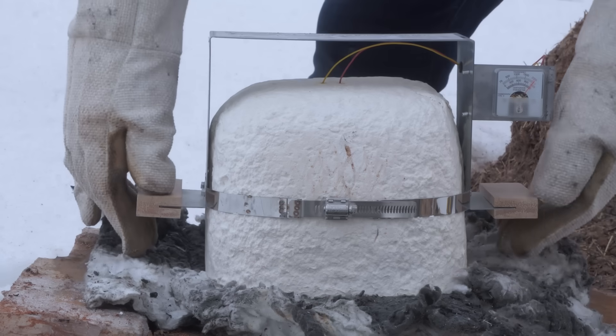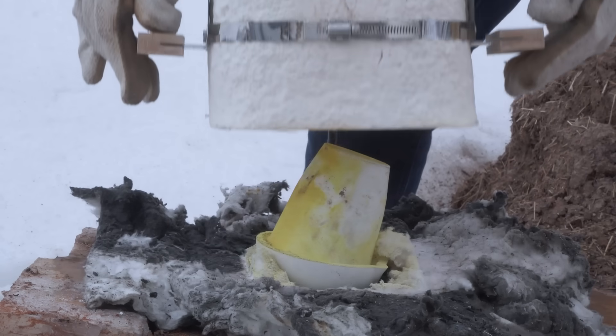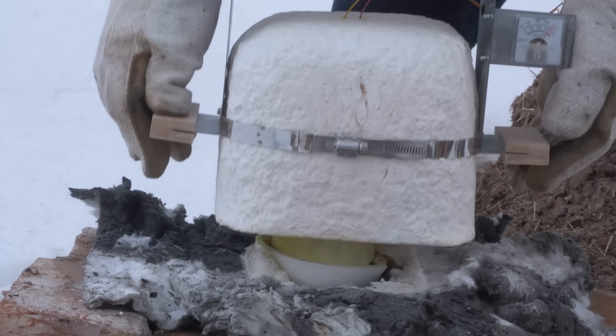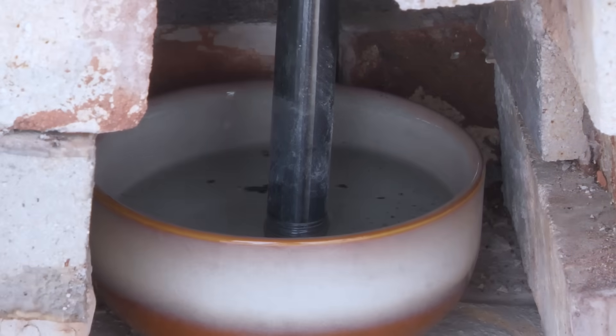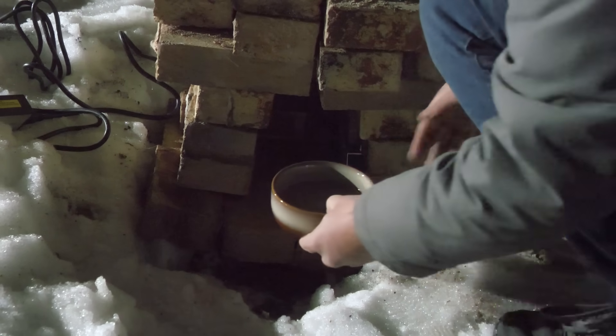So I was able to do the first test run of the zinc smelt, and the results are not super promising. Peeking inside the kiln, I could see yellow residue on pretty much everything. The zinc ore was escaping the crucible and leaking out of the edges, covering everything with a zinc compound on top.